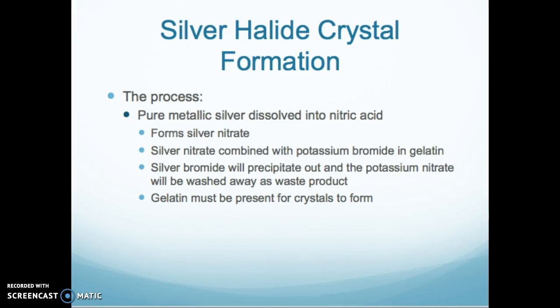So silver halide crystal formation. This is the process. Pure metallic silver is dissolved in nitric acid and forms silver nitrate. Silver nitrate is combined with potassium bromide. Silver bromide will precipitate out, and the potassium nitrate will be washed away as a waste product. The gelatin must be present for these crystals to form.